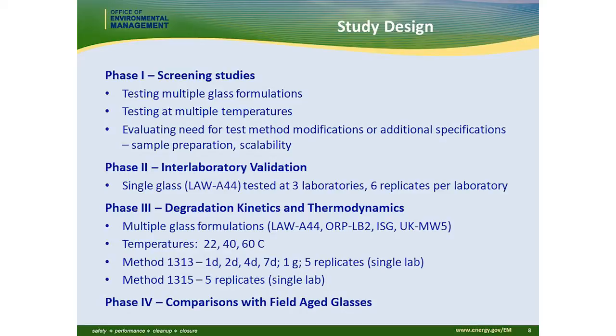We're focusing on a single glass, in this particular case what's referred to as LAWA44, tested at 3 laboratories and 6 replicates at each laboratory, and actually the replicates is 3 and 3 carried out at 2 different times in the same laboratory on the same glass.